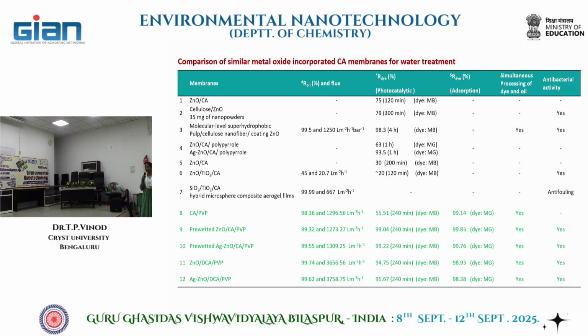Okay, so the entire setup cost us around 5 lakh only. I don't know whether I should say it's 5 lakh only, or it's like the glass half full and half empty. But actually you can make your own setup with much lower cost. What you need is a syringe pump, definitely, which can push this polymer solution at a controlled rate. And then a DC voltage source, any DC voltage source you can use, but the voltage is usually in the kilovolt range. So 10 kilovolts, it's possible. You can make it on your own. If you have a good engineering collaborator, very easily you can make it.